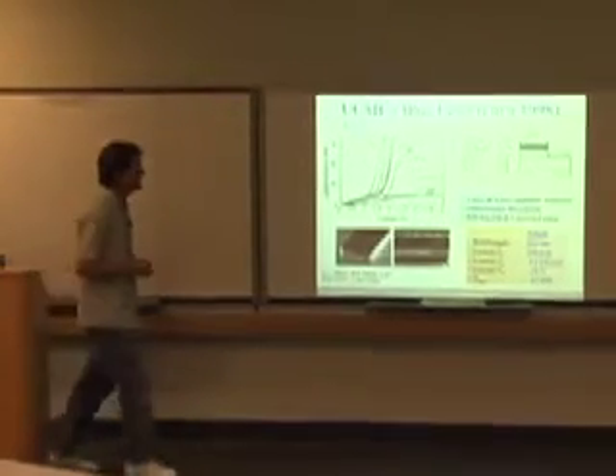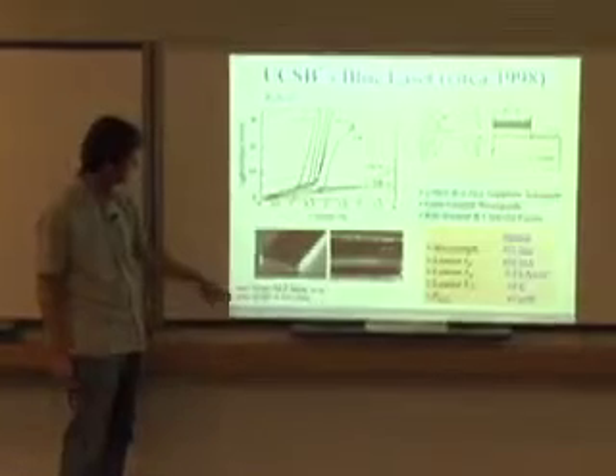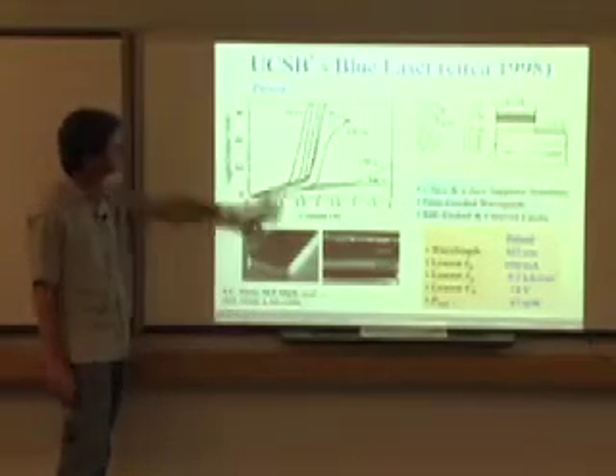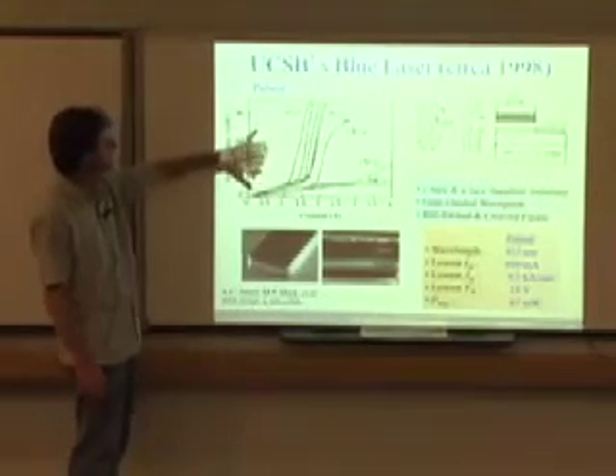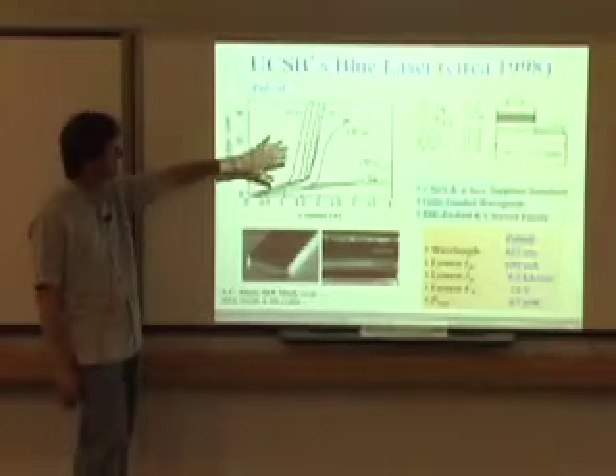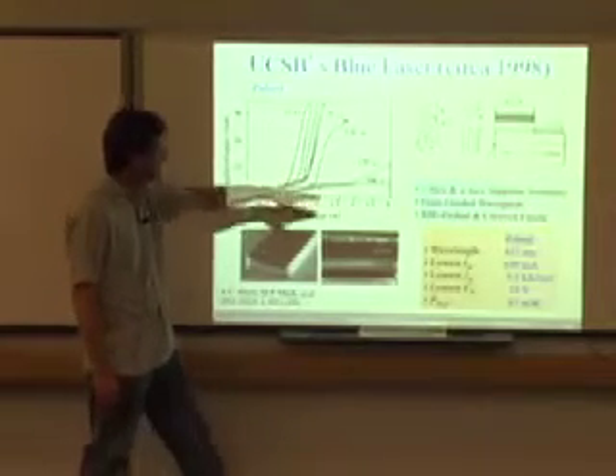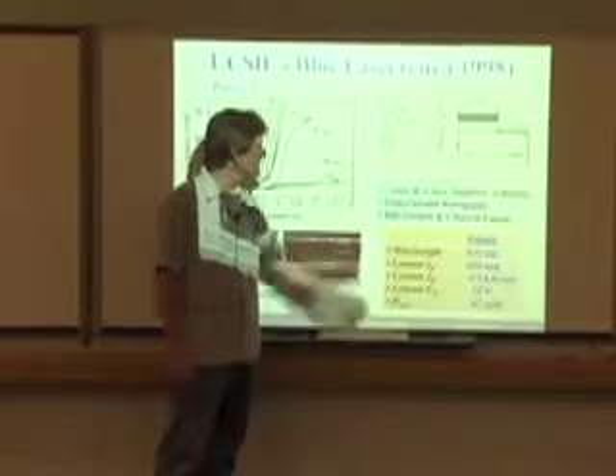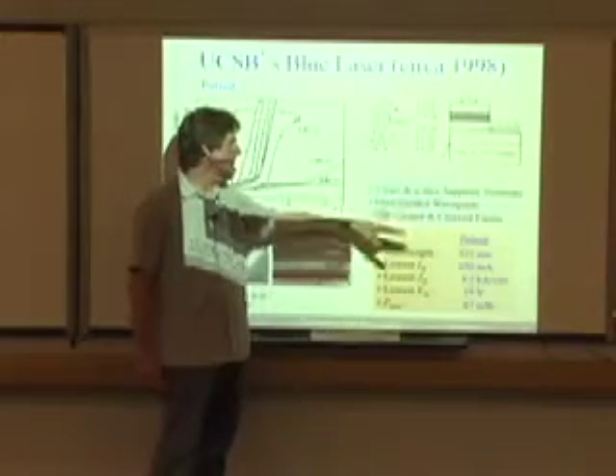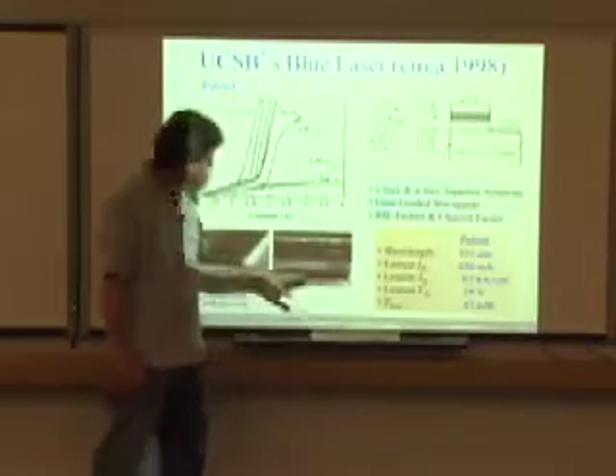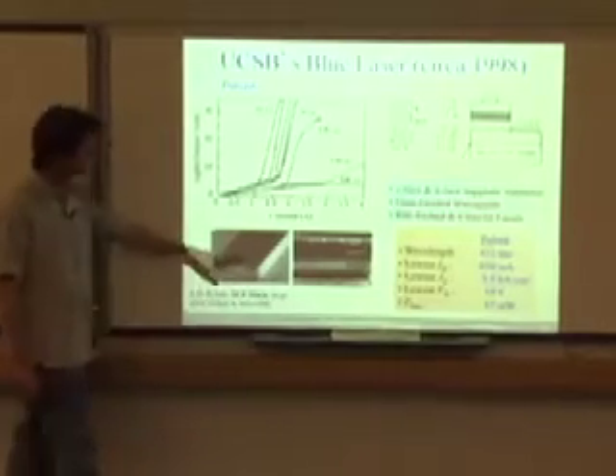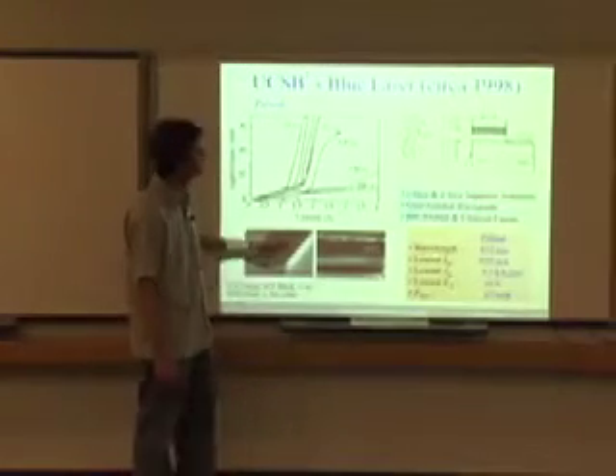They probably did. Then here we go, UCSB's blue laser, circa 1998. This is Abare and Mack reported this. This is a summary. I'm going to pull this not from the first publication they had, but they used both C-plane as well as A-plane sapphire substrates. And the nice thing on the A-plane sapphire was that they were able to use cleaved facets, as shown here. For the C-plane, they were using RIE etched facets here.